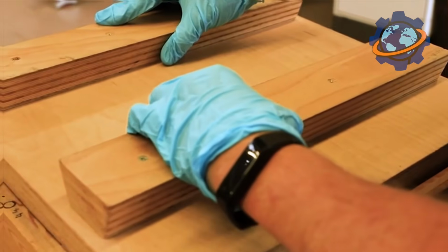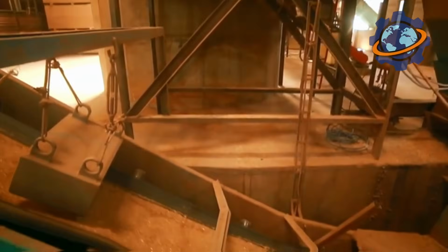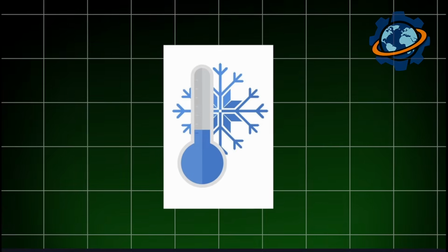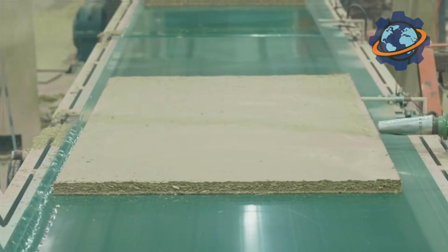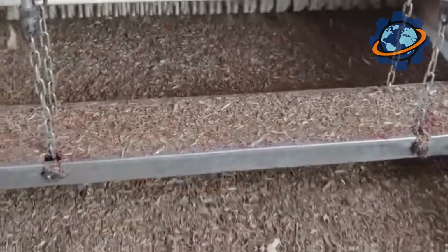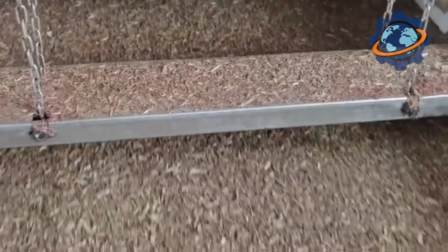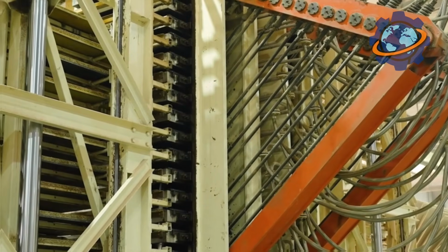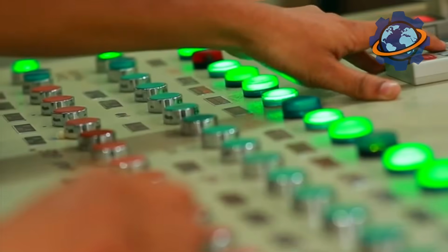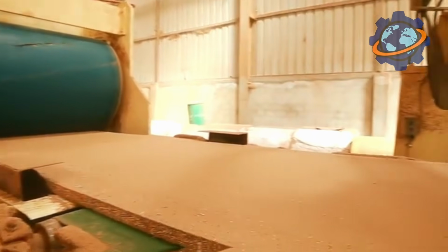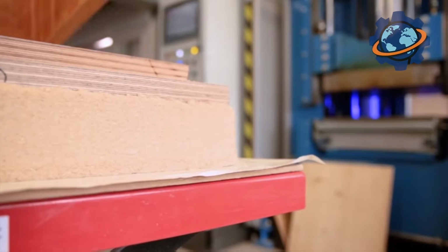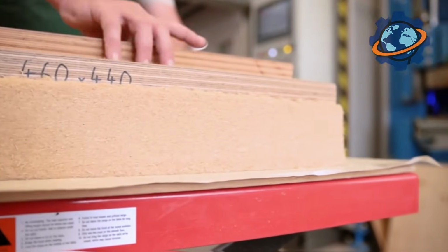The hot boards after the press cannot be stacked immediately. They need to be cooled gradually to relieve internal thermal stresses and avoid further deformation or warping. For this, they are placed in special star or fan coolers, where they are blown with air for several hours until they are completely cooled and their structure is stabilized. The next step is calibration and sanding, which gives the board a marketable appearance. The boards pass through sanding machines with several heads, where wide abrasive belts remove a thin surface layer, bringing the board to a precise specified thickness and creating a perfectly smooth surface.